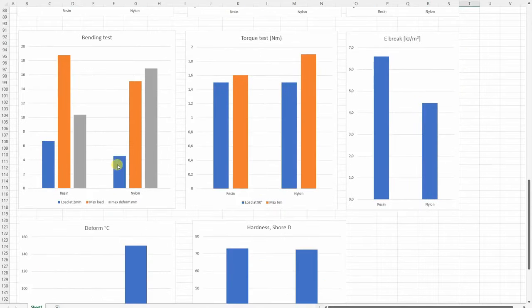With the bending test, I think the blue is the most important, the load at 2 mm deformation. So here the resin was stronger because it was approximately 6.5 kilograms until it reached 2 mm deformation. Interesting on torque test, usually I got very similar results like with the bending, but this time it was different. Basically the load at 90 degrees was very similar, almost equal with the 2 materials.